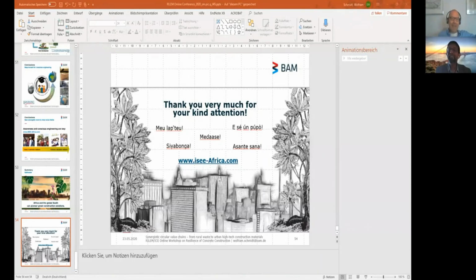Let's say it this way: certainly, this has an impact. But particularly if we use this two-step processing that I sketched at the end of my talk, if we use this pyrolysis step, and if we obtain the organics, or some organic parts, already before, we can avoid many of these problems. Sometimes a small retardation is even wanted, particularly at high temperatures. So these are all problems that exist everywhere in the world, and it's not easy to say there's one solution to get rid of that.